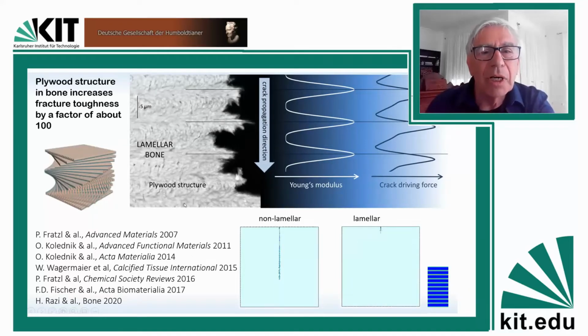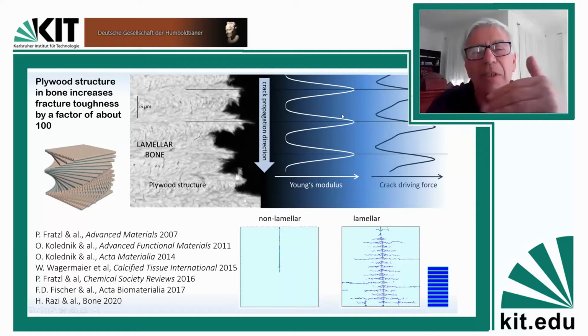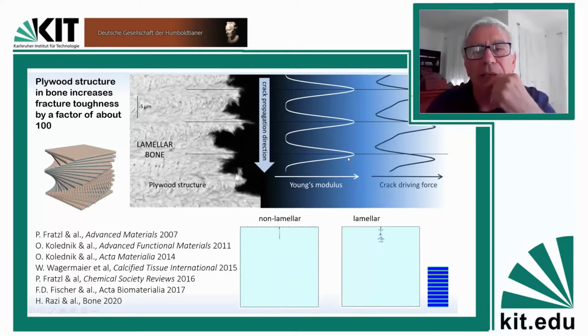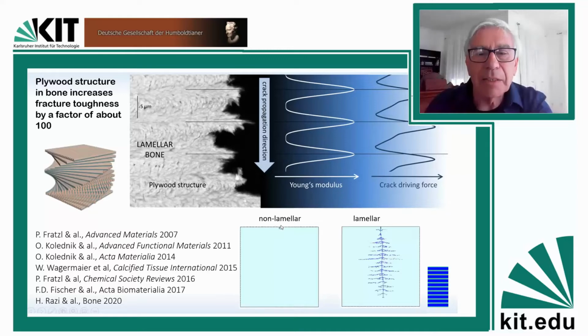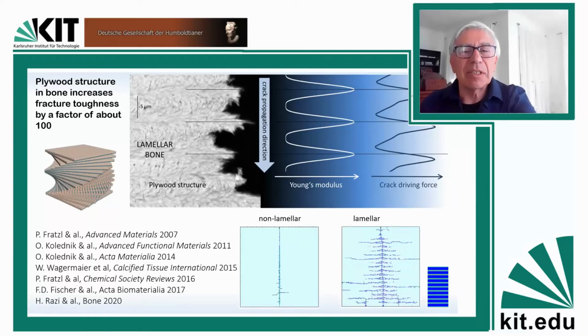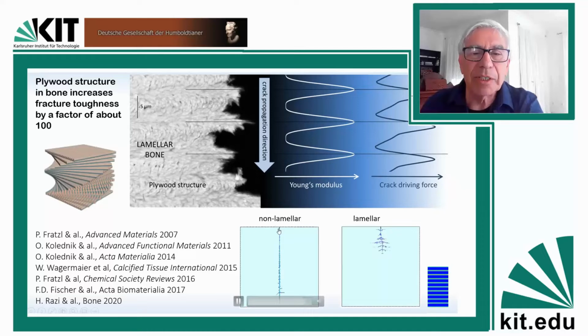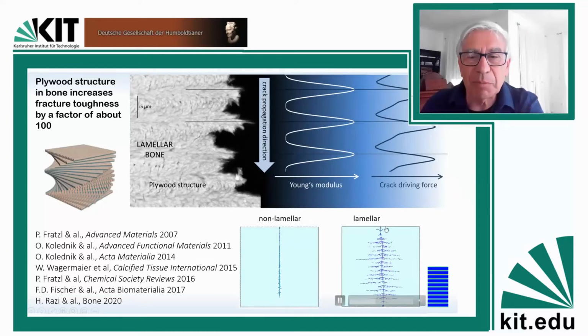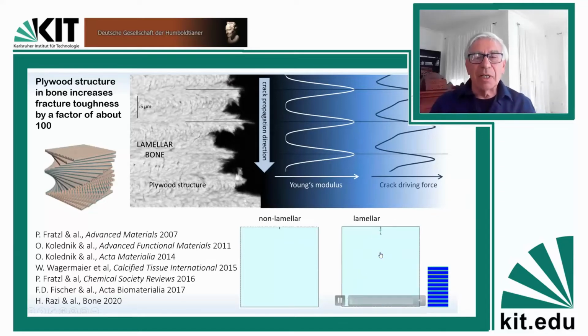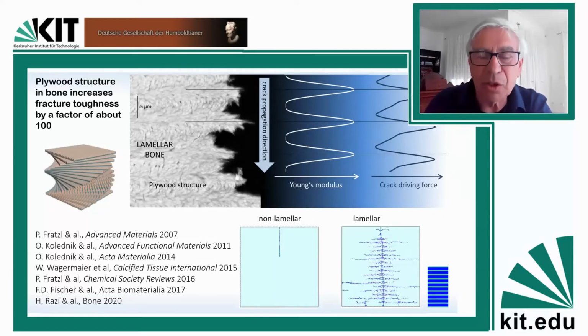along the bone, it experiences oscillations perhaps, or just alternating layers of hard and soft material, or stiff and pliable material. And if a crack propagates along such a structure, in a non-lamellar structure, you can see it moves in a straight way without any big resistance. In a lamellar structure, delamination occurs. The path of the crack is quite bizarre, and there is a high energy dissipation associated with that, so that the fracture resistance is strongly enhanced.